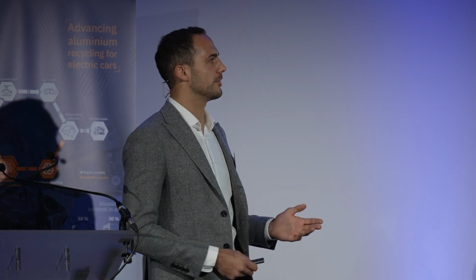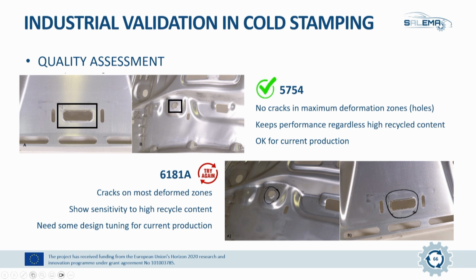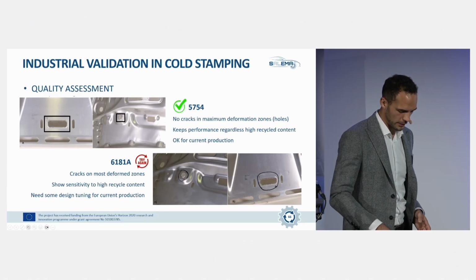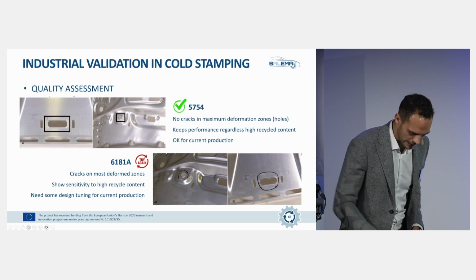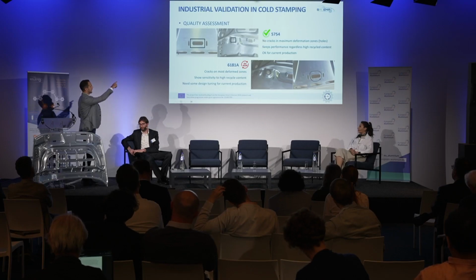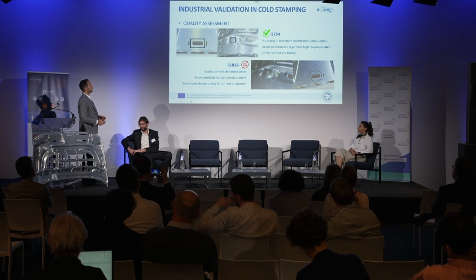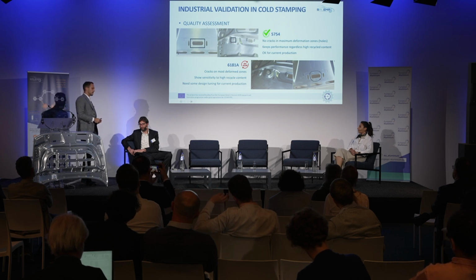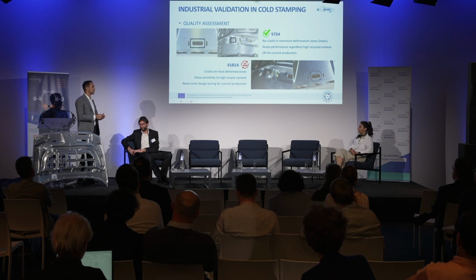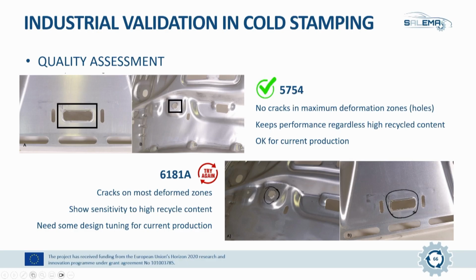And how it behaved: the 5000 alloy, I think this is this one, and outside there is the 6000 alloy. The 5000 alloy was almost perfect. We were not surprised, but very happy, because it could be used for current production since, from the manufacturing point of view, there were no defects. The highlighted ones are the most sensitive parts, because they are holes and so they can break up a bit.